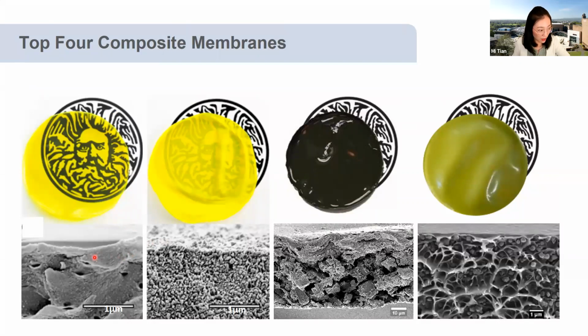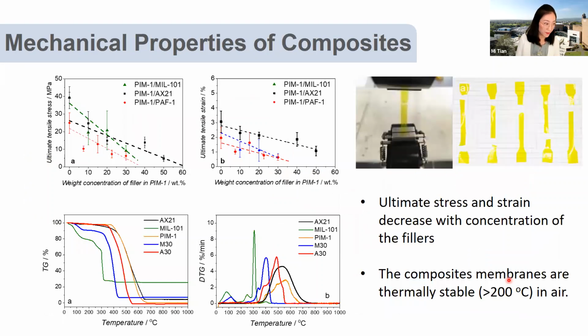So these are from the cross section of the membranes. We can see how the porous filler particles are homogeneously distributed within the matrix, and we can clearly see the boundary, the edge of the porous material particles. That tells us they are physically mixing, so there's no strong interaction between the filler and the matrix. That is a good thing, and is what we expected, because that will maintain the surface area and good adsorptive capability.